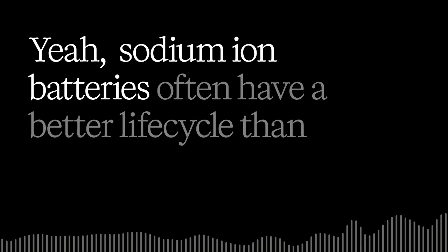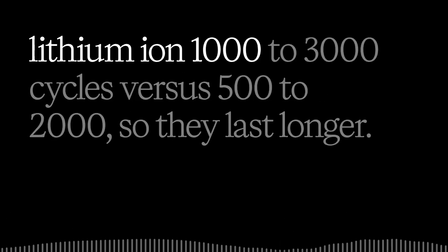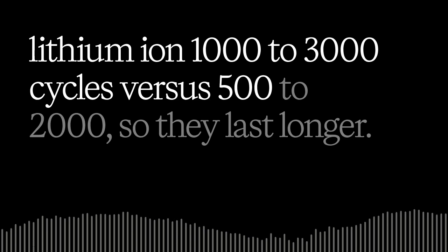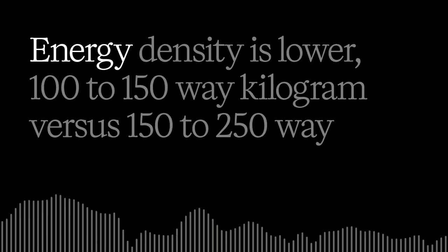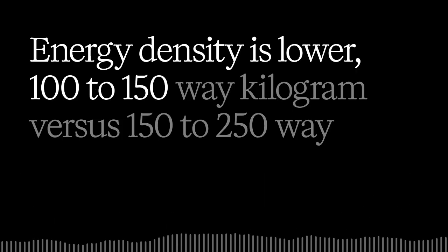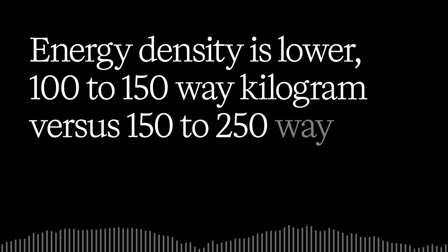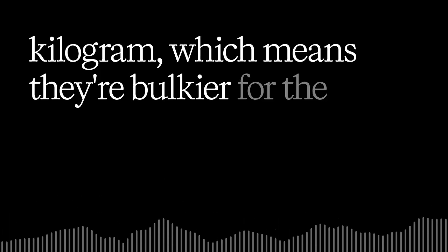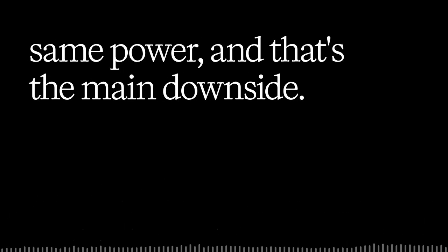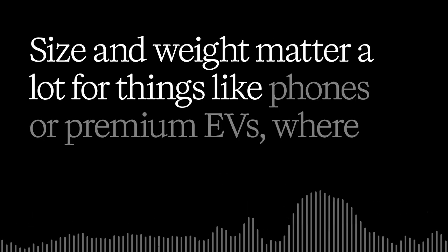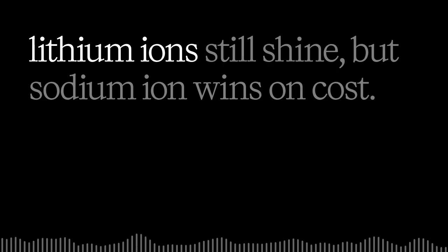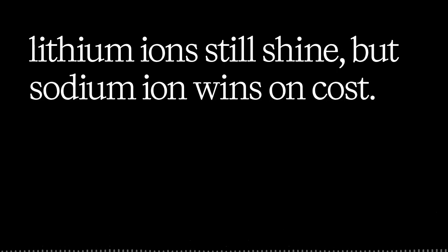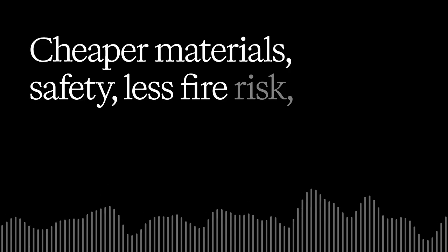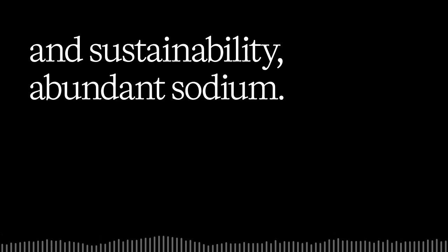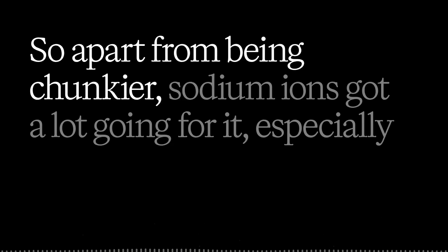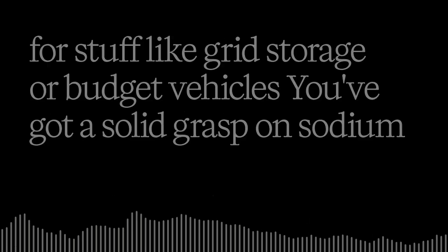Yeah, sodium ion batteries often have a better life than lithium ion, 1,000 to 3,000 cycles versus 500 to 2,000, so they last longer. Energy density is lower, 100 to 150 watt-hours per kilogram versus 150 to 250, which means they're bulkier for the same power, and that's the main downside. Size and weight matter a lot for things like phones or premium EVs, where lithium ion still wins, but sodium ion wins on cost, cheaper materials, safety, less fire risk, and sustainability, abundant sodium. So, apart from being chunkier, sodium ion's got a lot going for it, especially for stuff like grid storage or budget vehicles.